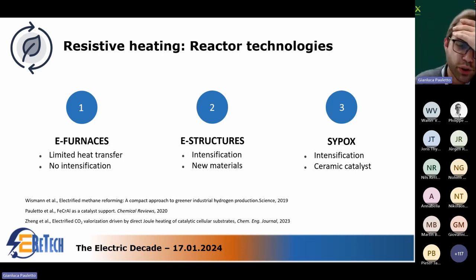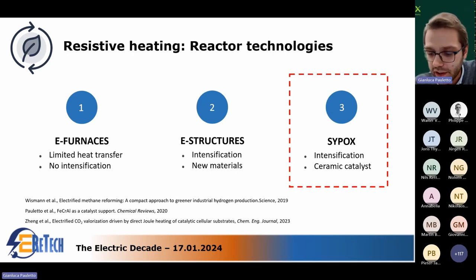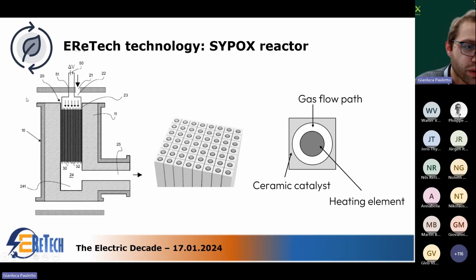And then we have another solution, where you use a ceramic catalyst and install within the ceramic bed heating elements that are in close proximity to the catalyst as well as in direct contact with the reacting gas. This is the technology that we are scaling up within the EReTech project. If we look a bit more in detail at what the reactor looks like, you can see that it is a cold skin pressure vessel with an internal refractory lining. Inside the pressure vessel, you are hosting an electrically heated catalytic bed, a sort of ceramic macrostructure having hollow flow paths where the heating elements are located.